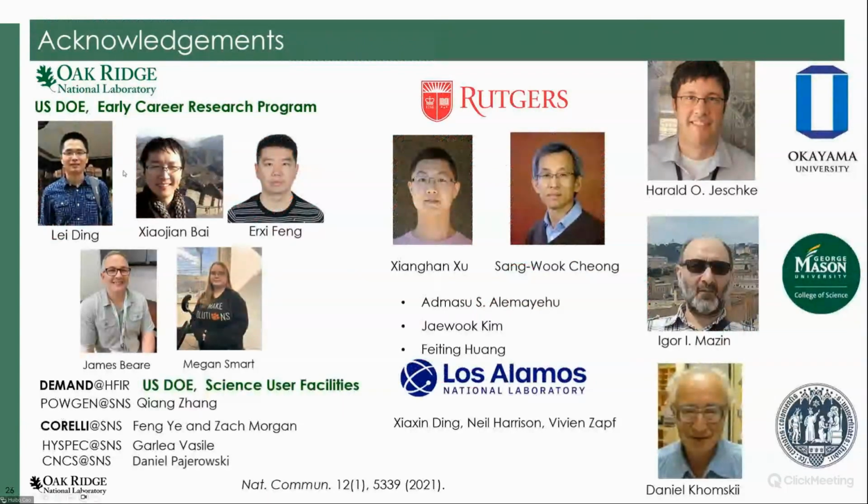Thank you very much for this excellent talk, which is now open for questions and comments. You mentioned single crystals. How big should the crystals be in order to get the kind of results you are presenting? For diffraction, a couple of millimeter size crystal is usually enough. But for inelastic measurement, our crystal is a gram or two, around 2 grams.